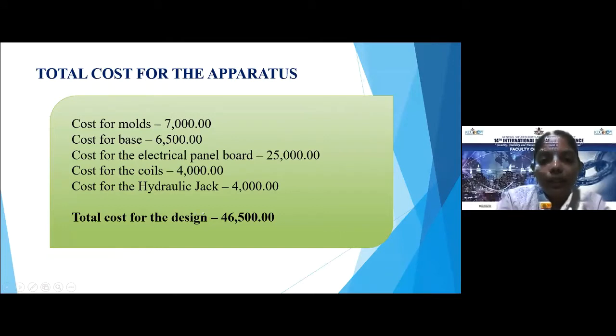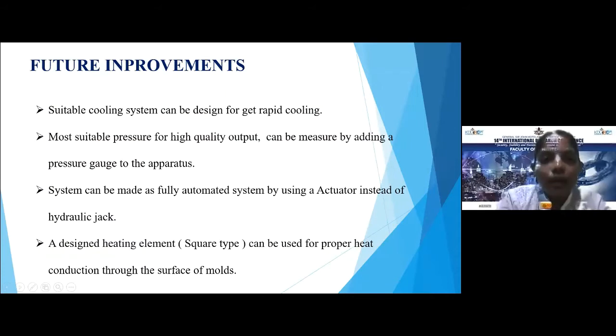The total cost for the design was 46,500. As a future improvement, I suggest a suitable cooling system can be added to get rapid cooling. If we add a pressure gauge to the system, we can measure the suitable pressure for a high quality output. This system can also be made fully automated by using a linear actuator instead of the hydraulic jack. And if we use the designed heating element, we can get proper heat conduction through the surface of the mold.